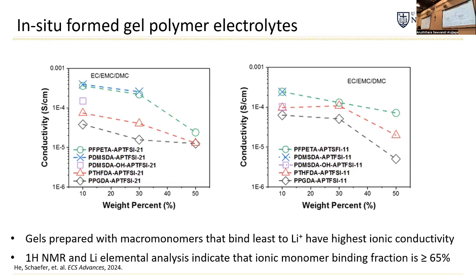We also tried to figure out, you know, these materials don't necessarily have to be pure single ion monomers. Because if the anions do not polymerize, if they do not react into the polymer network, then they would be mobile in the solution. So unity transference number is not guaranteed. Unfortunately, the electrochemical method, the Bruce Vincent Evans method, is really challenging with these types of materials because the carbonate solvents are so reactive. So we tried that method as well as NMR and some elemental analysis. We can predict that the ionic monomer binding fraction is at least 65%, so there may be some mobile anions in there. That's still kind of an open question.